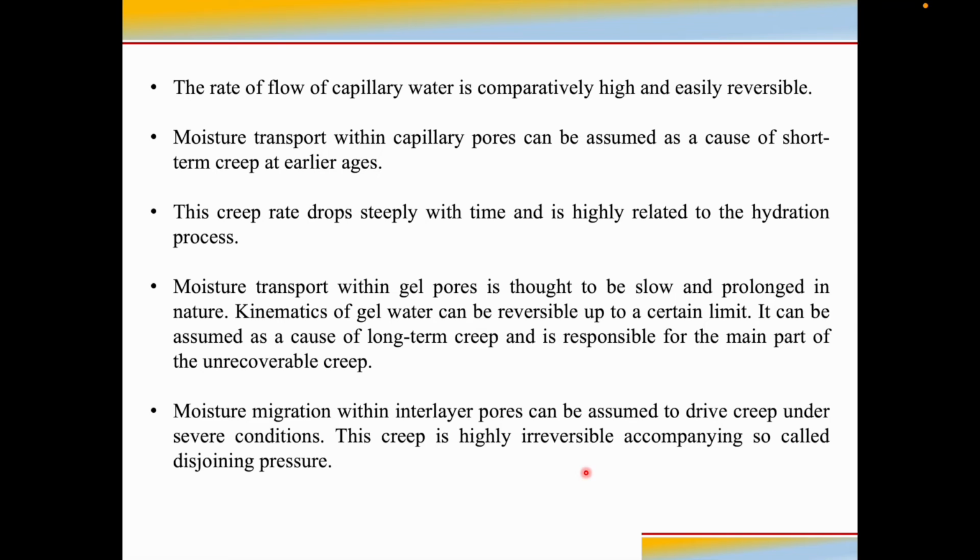Moisture transport within gel pores is thought to be slow and prolonged in nature. Kinematics of gel water can be reversible up to a certain limit. It can be assumed as a cause of long-term creep and is responsible for the main part of the unrecoverable creep. Moisture migration within interlayer pores can be assumed to drive creep under severe conditions. This creep is highly irreversible, accompanied by so-called disjoining pressure.